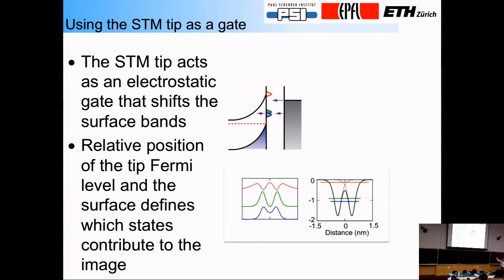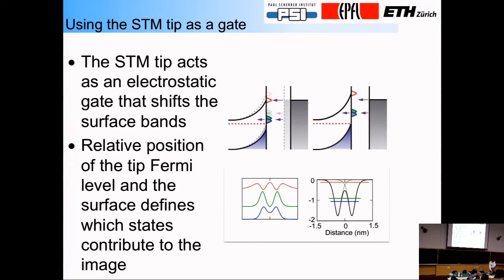So what I have here is this tiny quantum box that I fabricated, where I can tune the orbital state, simply by either tuning the tip sample voltage, or by shifting the Fermi edge relative to these levels. And the way I'm shifting it is shown in the upper part of the slide. As I shift it, I'm shifting the occupied states closer or further from the Fermi edge. And depending on where I am, I can either expose two blobs or a blob which contains mainly something in the middle with two side lobes. So I have electrical control here over the orbitals.